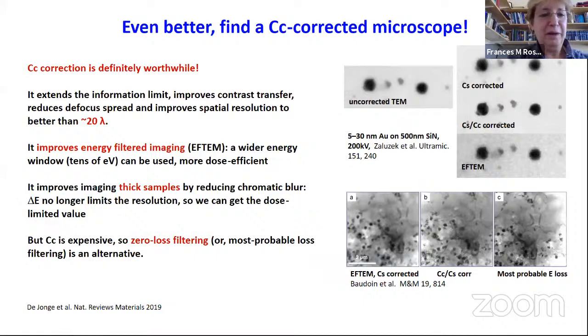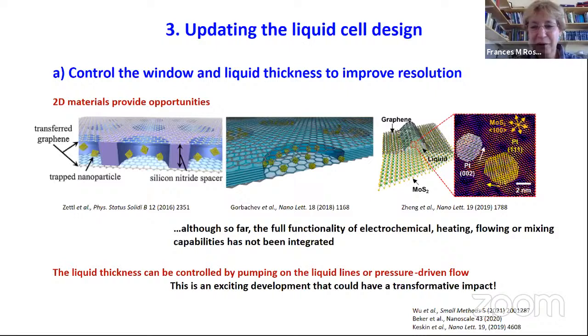If you can do chromatic aberration correction, you're definitely in a good place, because this helps a lot in terms of using all the electrons that maybe lost a little bit of energy in the sample. They would not be focused into a good image in a normal microscope, but a microscope with a chromatic aberration correction allows you to use all of the electrons, even the ones that lost some energy. So the only trouble is there's not many microscopes like this out there. And they're very hard to get onto, and maybe the users don't want you putting a liquid cell in there in case it breaks. So there are other ways around. You can do energy filtering, but if you do have access to this kind of microscope, that would be a good one to use.